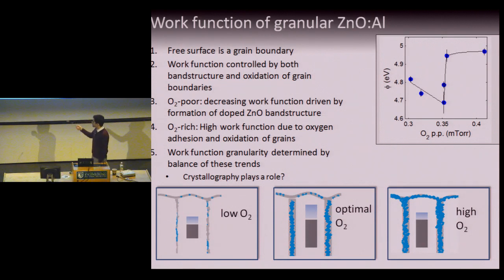For low oxygen content, the grains themselves are very efficient oxygen-getting materials. That is, they absorb oxygen into their lattice very effectively because they want to reach stoichiometry. As a result, you have very small amount of segregated oxygen defects along the grain boundaries, which in turn means that you have very little contrast as you scan over the top of this material and probe the work function over the grain boundaries as opposed to over the grains.